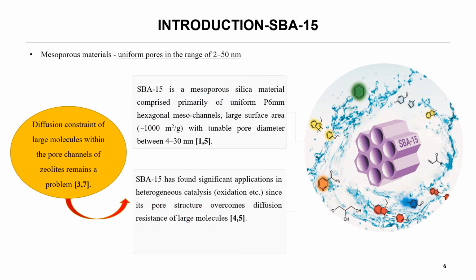Consequently, the focus of several research has been the selective synthesis of 2,6-dimethylnaphthalene and methyl-naphthalenes. Methylation of low-value naphthalene to 2,6-dimethylnaphthalene and methyl-naphthalenes is one of the efficient methods which has been proposed. Heterogeneous catalysts, specifically zeolites, with their varied structure, pore size, and acidity have been widely applied in this area. Even though zeolites such as ZSM5 possess high selectivity for 2,6-dimethylnaphthalenes, the conversion of reactants and yield is low due to the diffusion constraint of larger molecules within the zeolite pores.